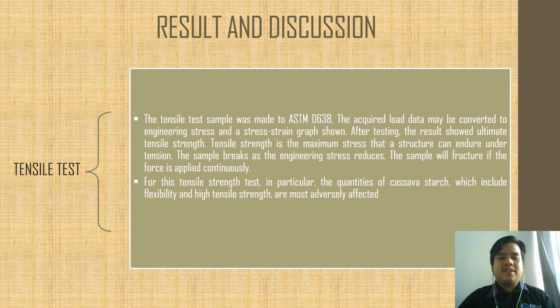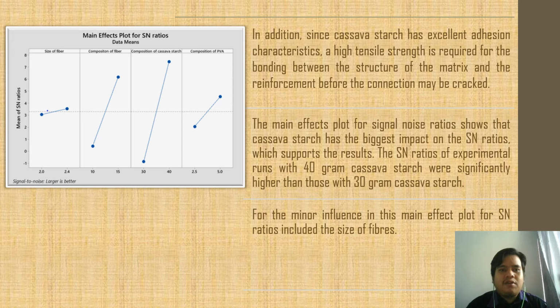For this tensile strength test in particular, the quantity of cassava starch, which provides flexibility and high tensile strength, is most adversely affected. This is the figure of the main effect plot for signal-to-noise ratios created from Taguchi analysis in Minitab. In addition, since cassava starch has an excellent adhesive characteristic, a high tensile strength is required for the bonding between the structure of the matrix and the reinforcement before the connection may crack.